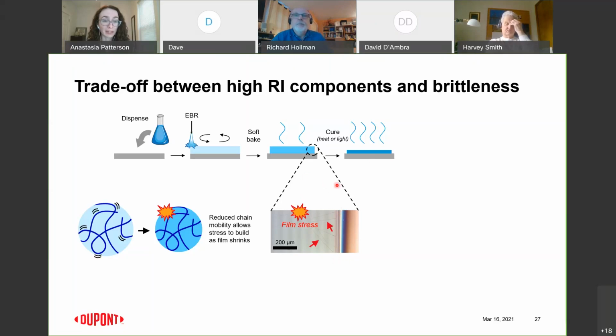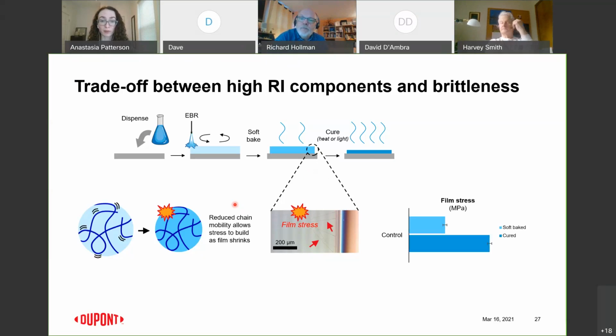So we're already getting cracking at the soft bake step, and this is due to that reduced chain mobility. A lot of the solvent has been evaporated, so there's enough reduction in the chain mobility that we can't actually relax the stress that's being induced. We can measure the film stress at the soft bake and cured steps. And so you can see that the stress does increase quite a bit in the cured film, but there is significant stress in the soft bake film. So this bar is what we're going to be trying to target and lower.